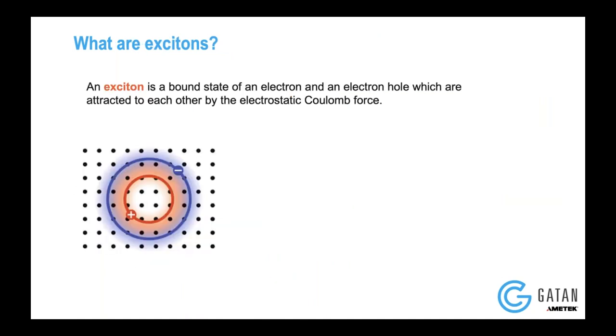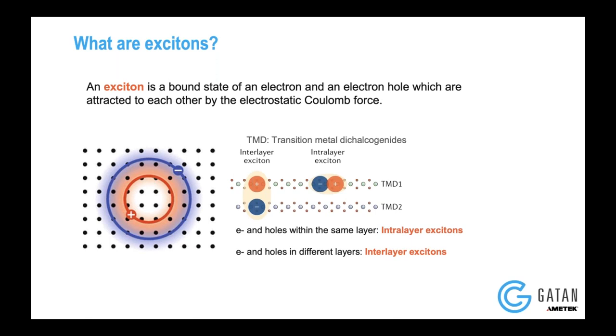I'll be talking about a specific case study we did with low-loss EELS, which is measuring excitons in two-dimensional materials. An exciton is a bound electron-hole pair, attracted by Coulombic forces of interaction, and you can have various radii of exciton — meaning it can be delocalized in space in a normal material. In two-dimensional materials, you have two kinds of excitons: the intralayer exciton and the interlayer exciton. In a trivial sense, you can imagine excitons to be little dipoles — intralayer excitons are oriented in the in-plane direction, whereas in the interlayer exciton, you have it out of plane.